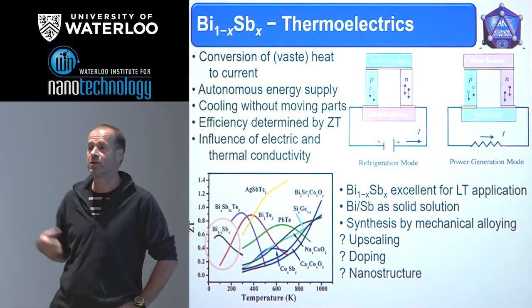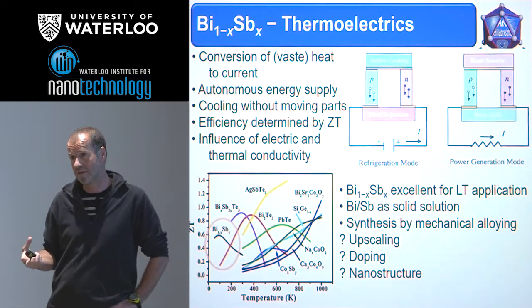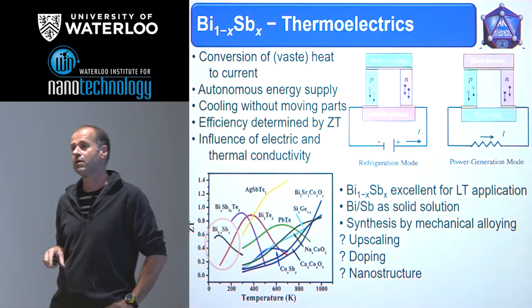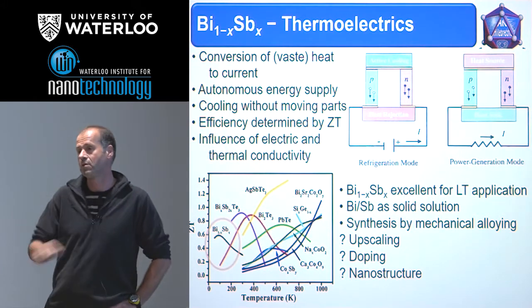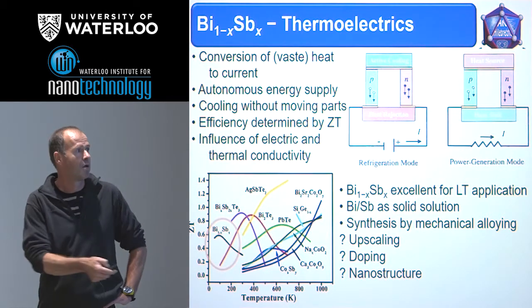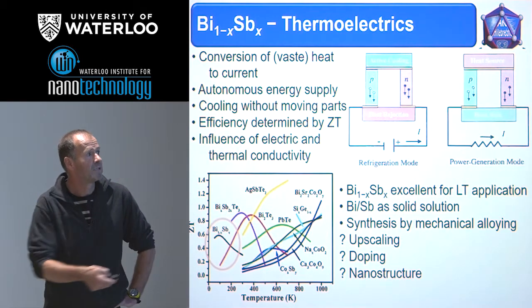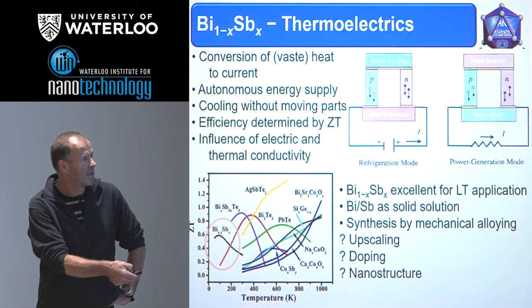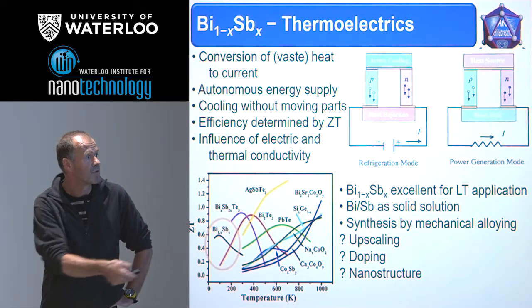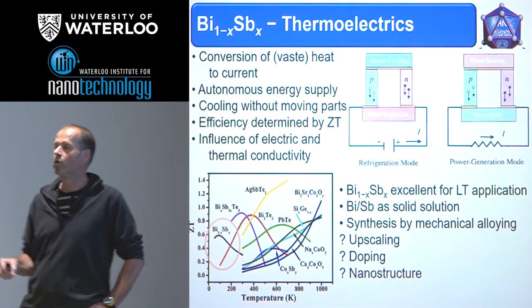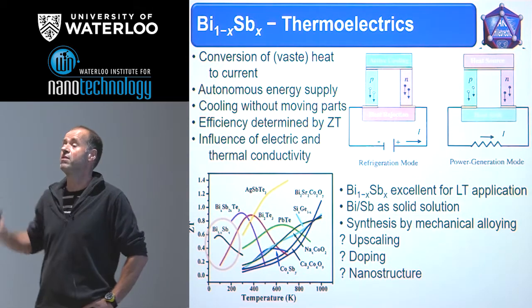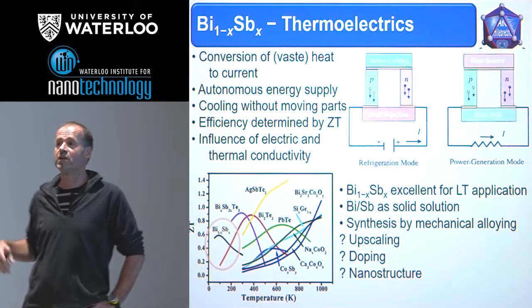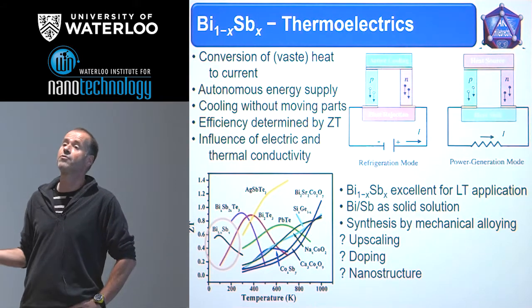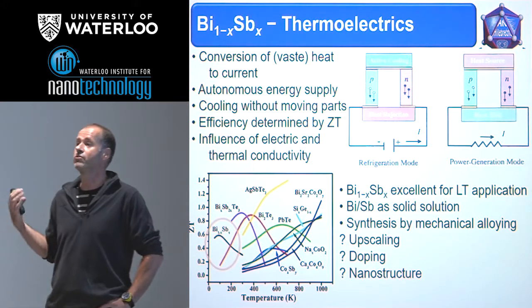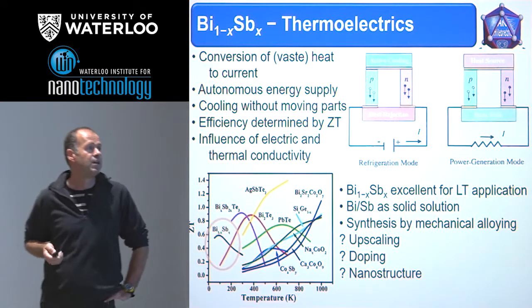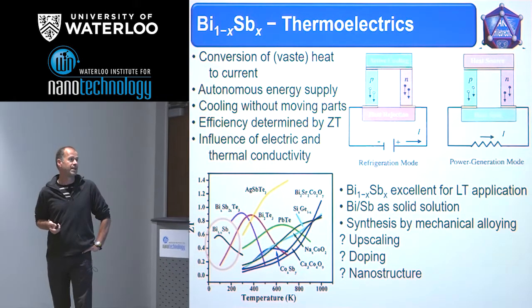And we developed a process which gave nanomaterials for the bismuth telluride, which worked quite well. And so we asked, why can't we skip the telluride, just do solid solutions of bismuth and antimony? And the idea is quite clear. At very, very low temperatures, around 100 Kelvin, it's the only good material for these very low temperature applications. And nobody wants to generate energy at these temperatures. Now we have the idea with the cooling device, and cooling to very low temperatures should be possible if we have quite good materials for that.